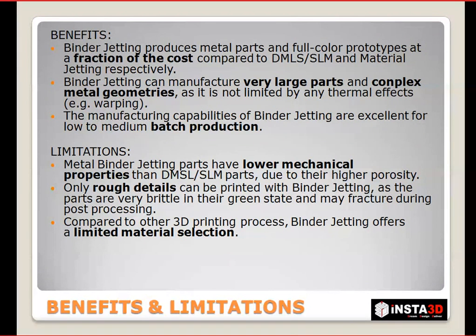And the limitations are that you have lower mechanical properties when compared to DMLS and SLM technology, because of the high porosity of the 3D printed part. And to reduce the porosity, we sinter or infiltrate the part with other materials. Intricate details cannot be printed using a binder jetting 3D printer, and the part will be very brittle in its normal 3D printed green state, and may fracture during post processing. So care should be taken that you do not put the part down roughly, as it can get damaged easily. Until sintering and other post-processing techniques, the part will be very brittle in nature. And compared to other 3D printing processes, it offers very limited material selection as well.